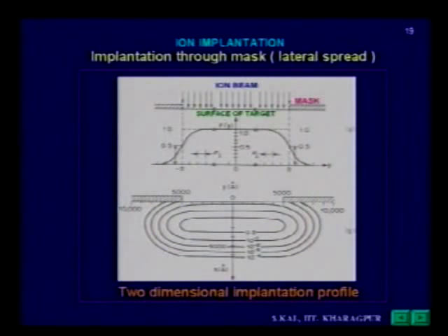That means the only problem is the tail region, either the surface tail or the deep tail into the substrate. So both tails give some problem in the Gaussian distribution, which is an approximate distribution profile given by LSS. But both arsenic and boron tails exactly match with the Pearson 4 or four moment approach. Now, next we'll discuss implantation through a mask.